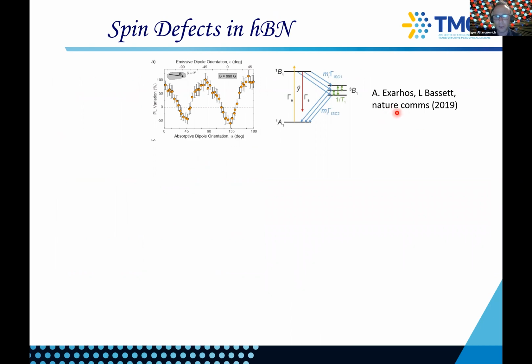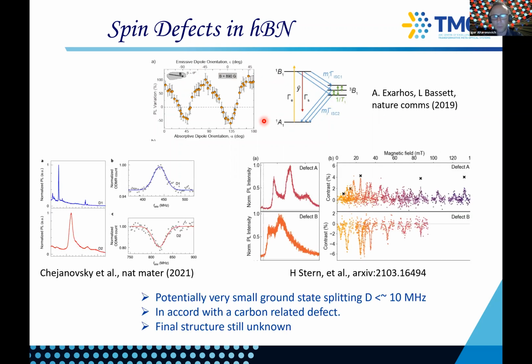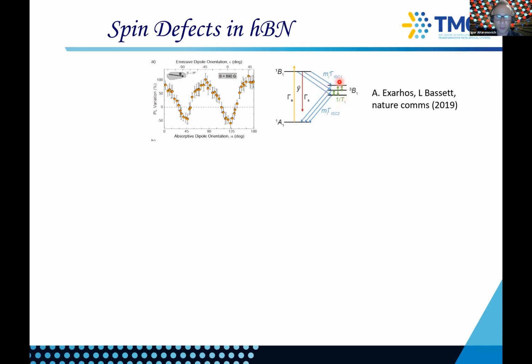So back in 2019, the group of Lee Bassett, they realized that some emitters show this magnetic field dependency. And what they did is basically they put the magnet and rotated the magnet, and they saw that the PL emission alternates. And so there was no optically detected magnetic resonance, just a response to the magnetic field, which they explained based on a singlet and a triplet transition within the metastable state. So this is very similar to some molecules, for example.